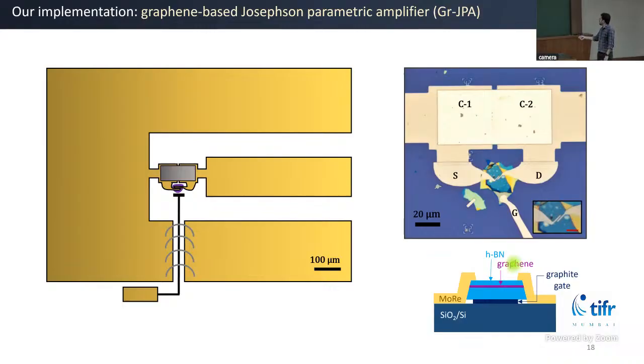So our samples are edge contacted. The graphene is sandwiched between two hexagonal boron nitride layers. That's for mobility enhancement and chemical protection of the graphene. And then we make the contacts through this etching method. At the side, we deposit two superconducting leads, this MoRe, which is a type 2 superconductor.